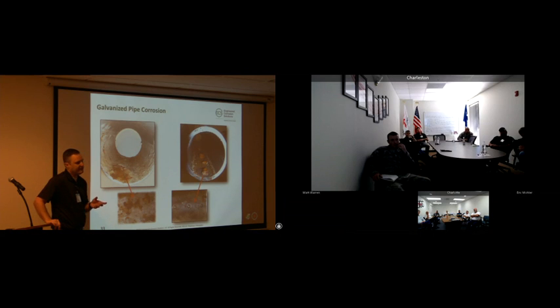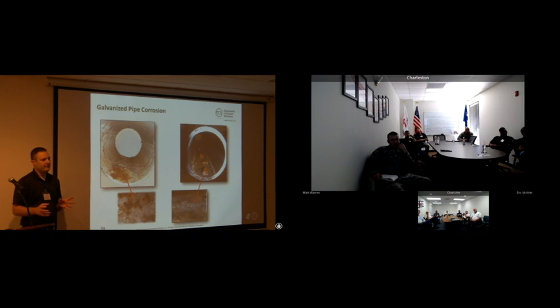What we found out was because corrosion's cumulative, when we're putting in 98% nitrogen, we're still putting in 2% oxygen. You put in 2% oxygen for 18 months, you're worse off than if you would have just put an air compressor on it and just let the system naturally leak. Because we were inducing a leak rate with our vents, thinking we were drying the system out, we just let it vent continuously. You can't dry out a system with nitrogen. There's just too much water in it.